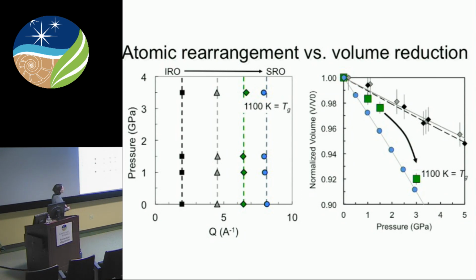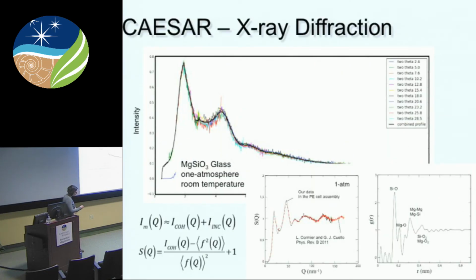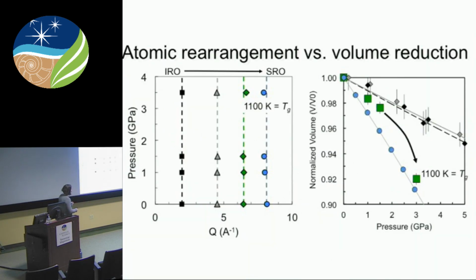And we took CAESAR diffraction patterns at these same PT conditions. Anyways, the moral of the story is that we're tracking the position of these different peaks for Mg-Si-O, or different magnesium silicon oxygen bonds. We have 4 different peaks, and what we see is that as we compress it and as we heat it, nothing moves. So the volume reduction is being accommodated by something different.